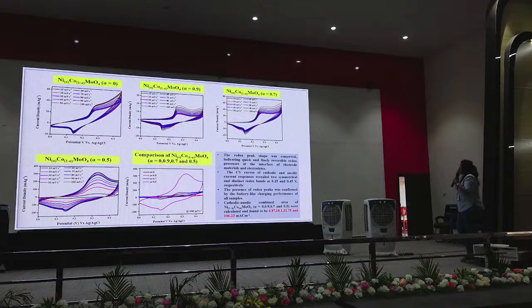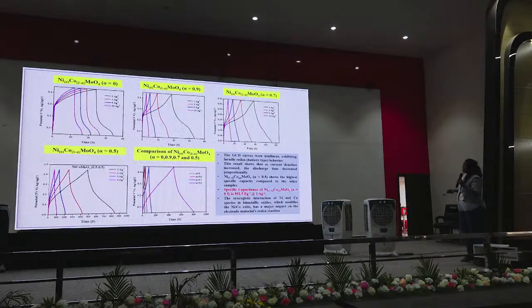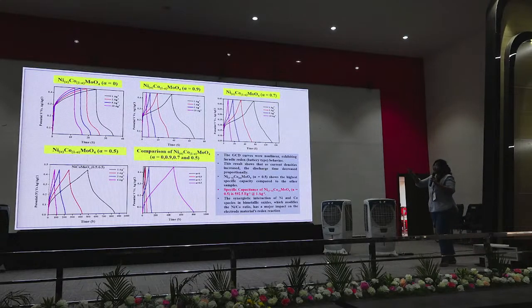Here, from the CV graph, I have got the integral area of the CV. Again, the different current densities were applied to all three percentages of nickel incorporation, and this is what we got. And the last one is about the nickel cobalt molybdate at 0.5.